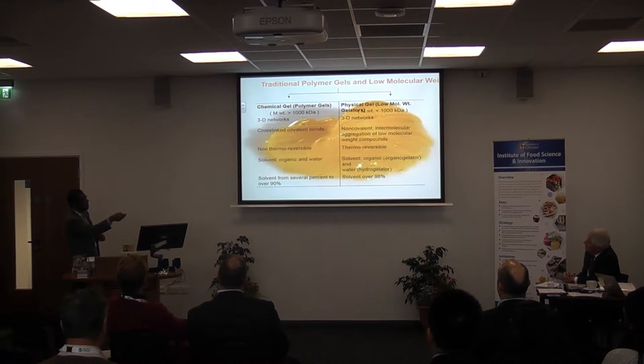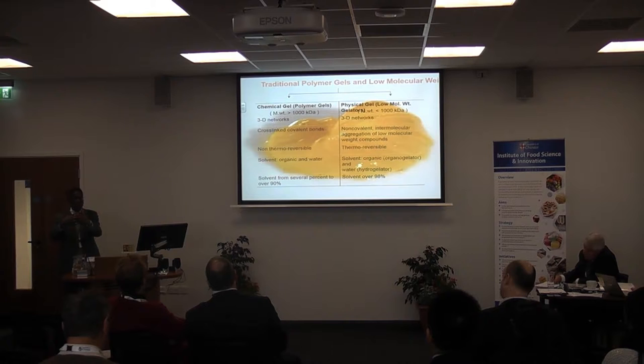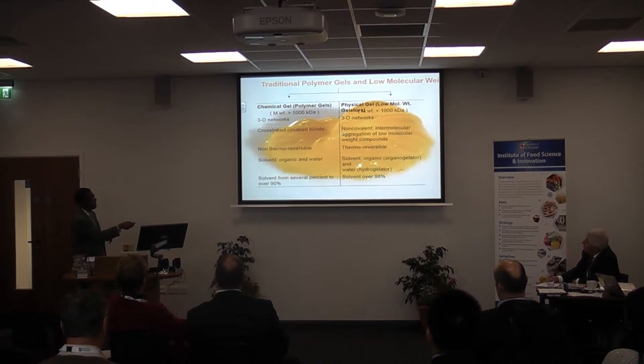And I'm going to talk about how we can create gels from very small molecules, assembling together to create a polymeric structure, but it is not a carbon-carbon polymer. It is by the weak forces of nature, what we call the non-covalent interactions. And because these are created from non-covalent interactions, they are thermoreversible. That means if you heat it, it will just melt. If you cool, it will come back. And we can create water-based gels, we can create oil-based gels.